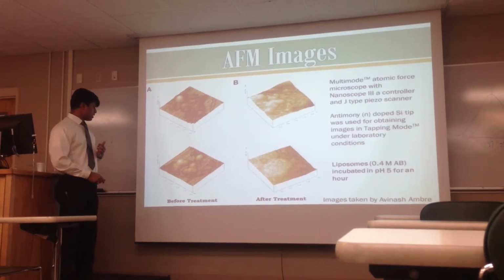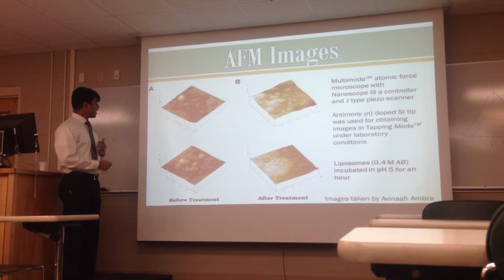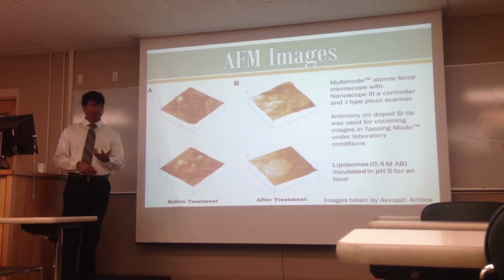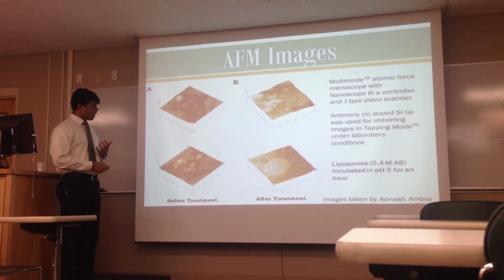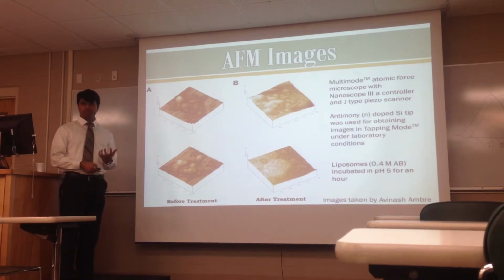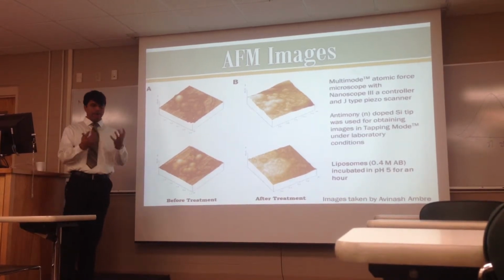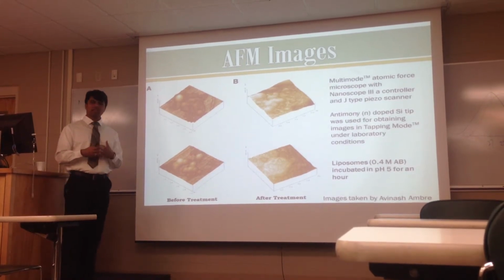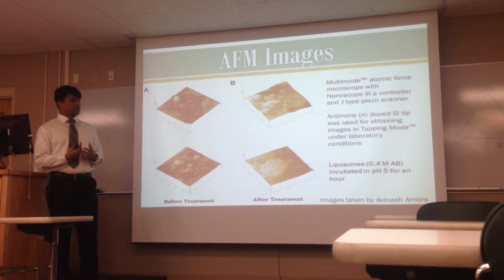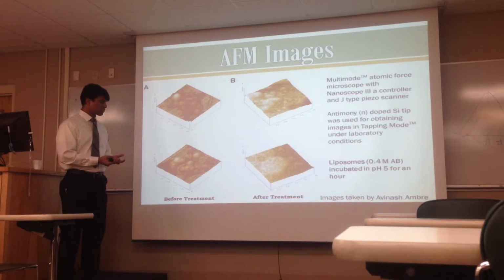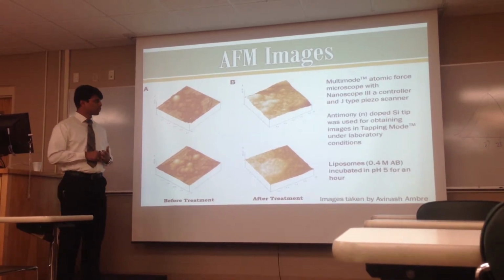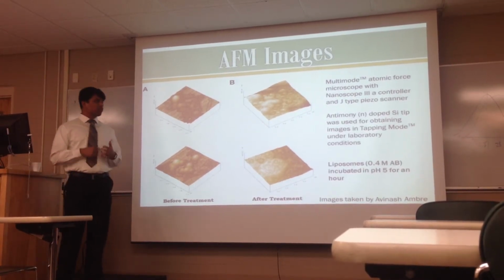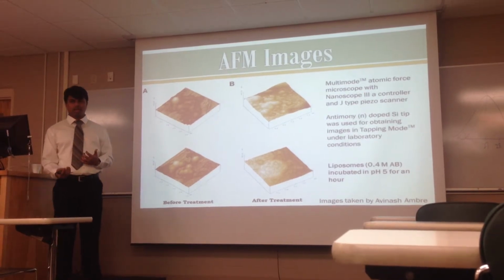As you can see, before treatment the liposomes are round, nice, spherical, like a boiled egg. But after treatment, it looks like a scrambled egg. The bilayer structure gets completely destroyed, indicating that the escaping carbon dioxide bubble does have an impact on the bilayer structure, releasing the content. And after that, we wanted to make sure whether it releases the content or not.